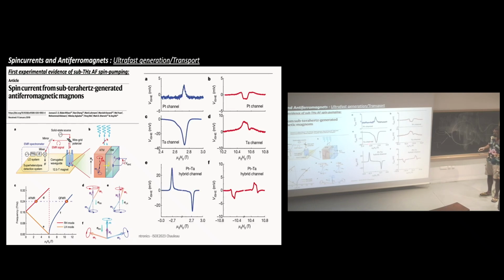They nicely measure, actually, at a given field, an inverse spin Hall voltage, which is the signature of the fact that a spin current has been injected into the platinum. The nice thing is that it reverses with tantalum, which has opposite spin Hall effect. So this is a nice proof. And then to enhance the signal, they made some kind of hybrid channel, but this is not really the point. The nice thing is that they also see the mode in the quasi-ferromagnetic regime, where the antiferromagnetic material is flopped.